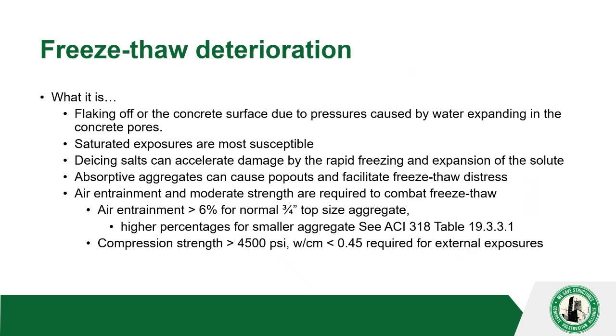It is from the outside in. So in order to keep that from becoming a problem, you have to have air entrainment, and you have to have good compressive strength and a low water cement ratio. And with the use of pozzolans, you probably need to cure the structure a little bit longer with the supplementary cementitious materials when you do a new job. What happens sometimes is you'll pour concrete with fly ash in it, and it's not cured long enough, and it doesn't reach its 28-day strength, which is in a moist cure room, right? So if this is what the cylinders say, it's not necessarily what's happening on the structure if it stops curing after like 3 days.